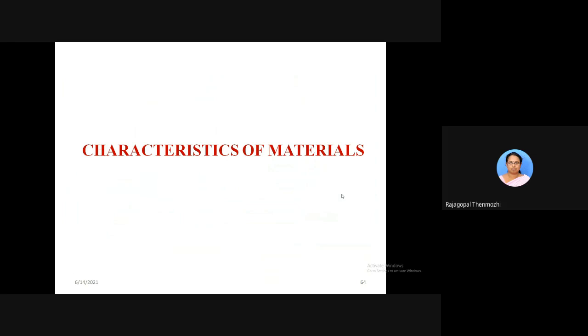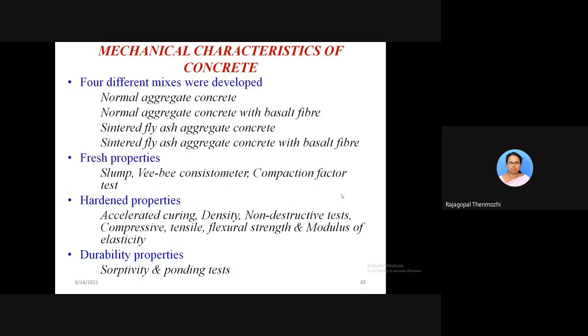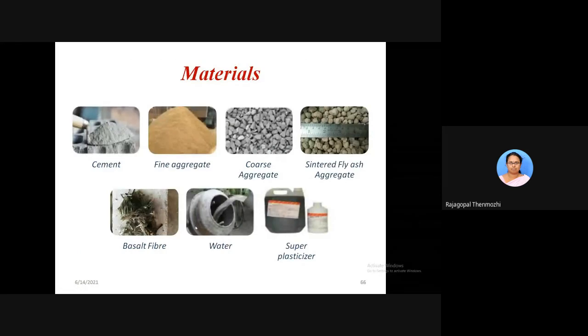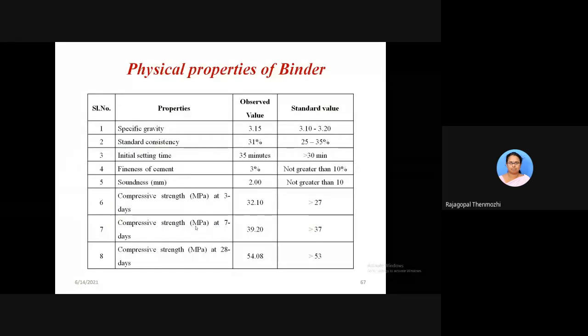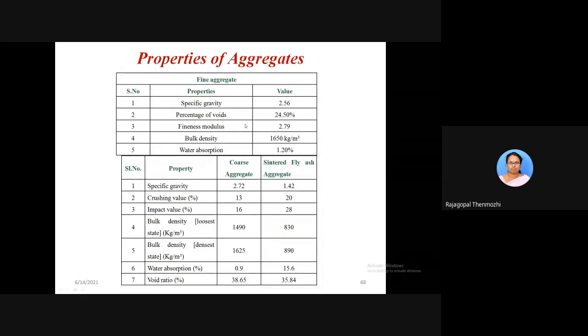Coming to the characteristics of materials, they have used four different mixes: normal aggregate concrete, normal aggregate concrete with basalt fiber, sinter fly ash aggregate concrete, then sinter fly ash aggregate concrete with basalt fiber. They did all the fresh and hardened concrete properties along with durability. These are the different materials used in this investigation and the various physical properties of the binder. And these are the different values of the coarse aggregate and the manufactured aggregate. Here we are finding the values of the conventional coarse aggregate and also the sinter fly ash aggregate.